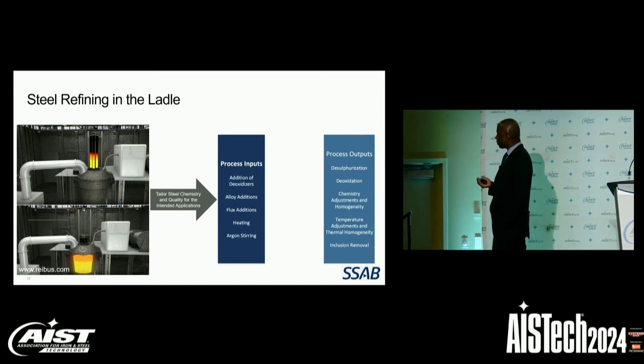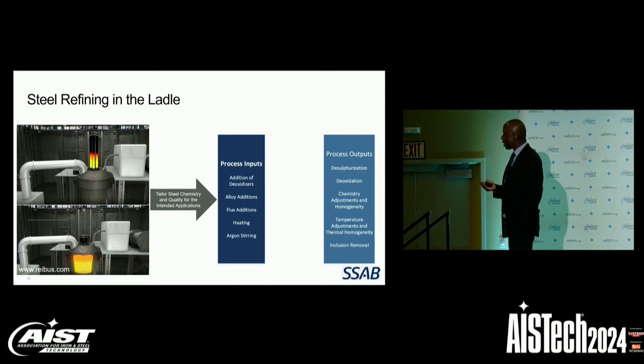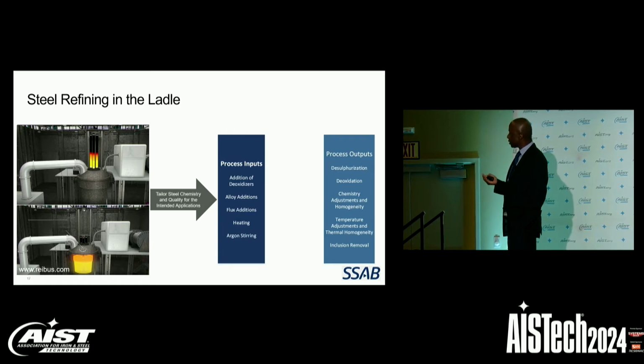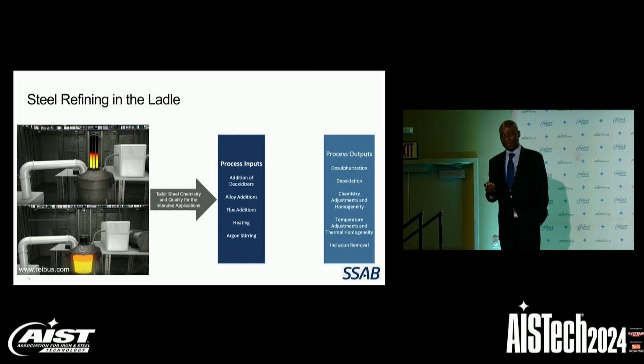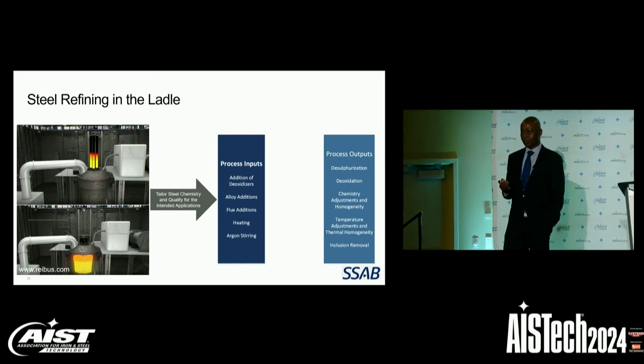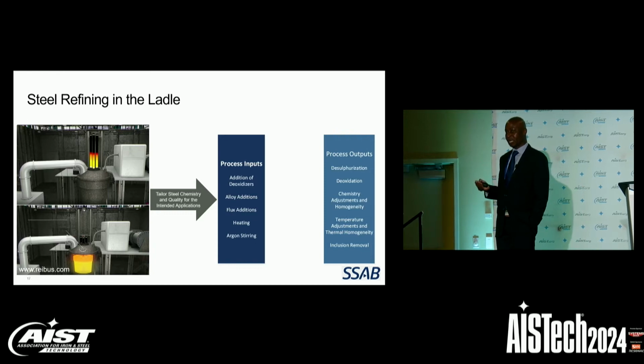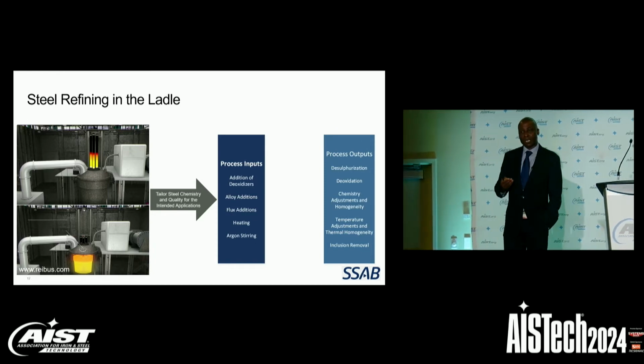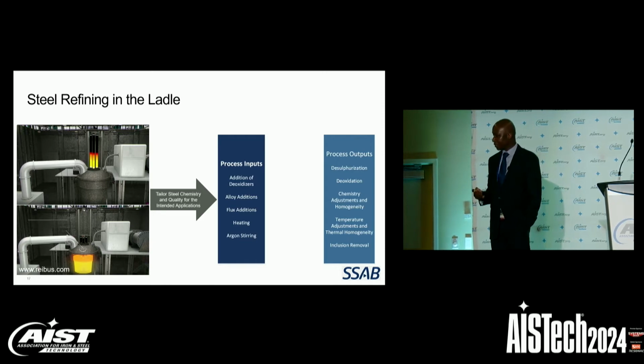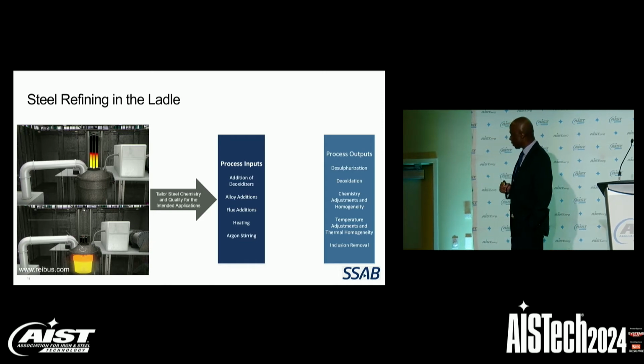The operators have to ensure that they add adequate amount of deoxidizers and fluxes for efficient desulfurization and deoxidation. They have to ensure periodic addition of multiple alloys into the ladle as they sample the steel to test the chemistry to ensure that the chemistry is within the specification that is required for that particular grade.